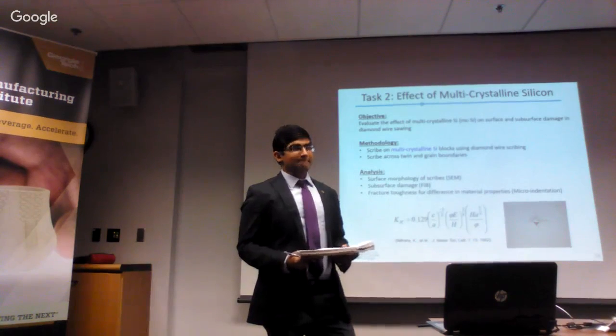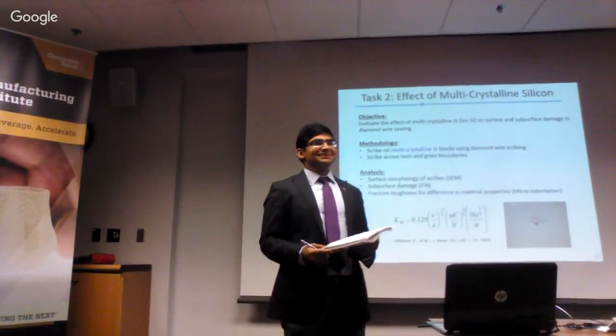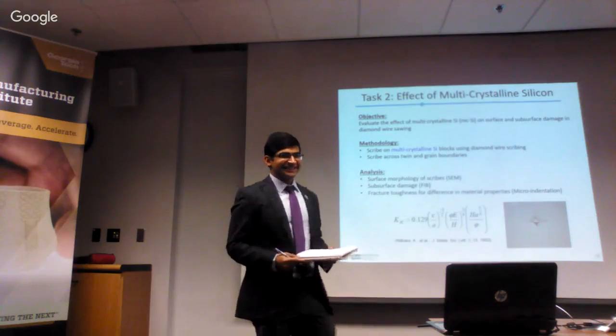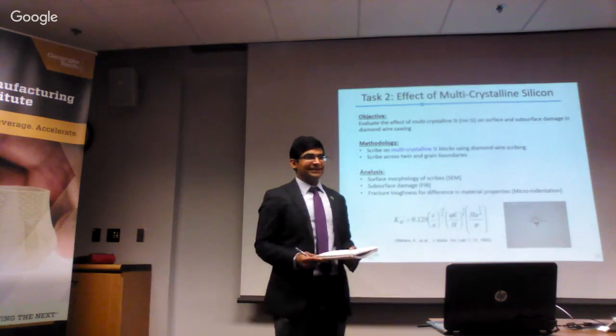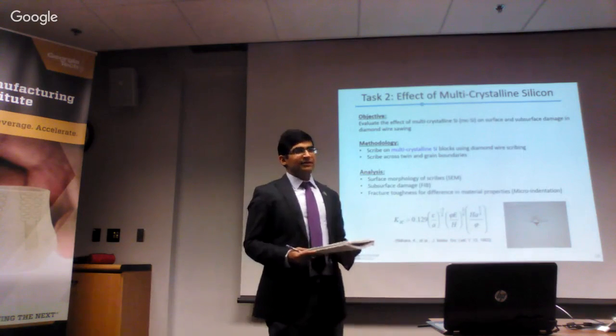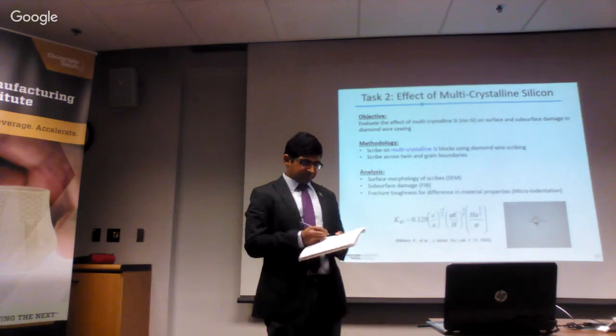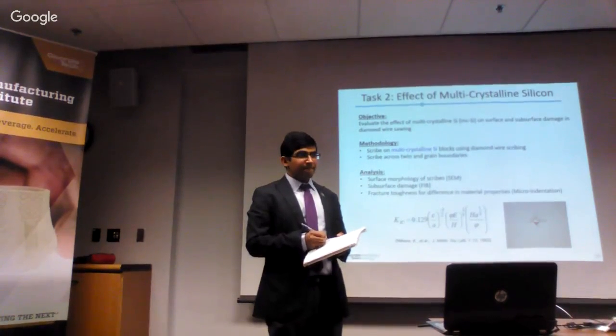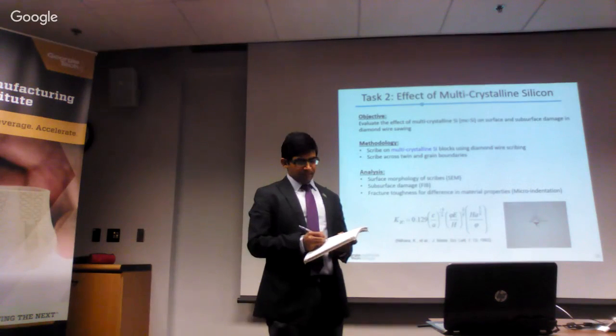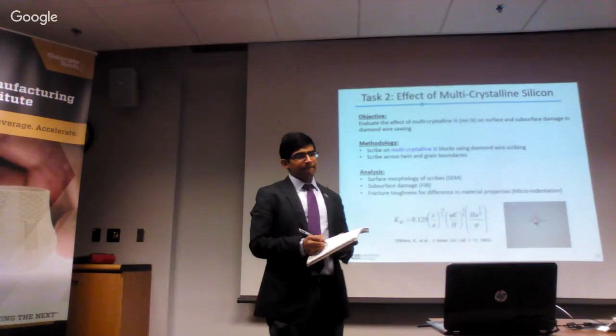I'll make one more comment about this, and we've got to get off this topic. The reason we in my group never pursued this dislocation explanation is because dislocations are not active in silicon at room temperature. You've got to get up to about 750 centigrade before dislocations actually are generated. So we didn't feel like we could explain it by a plastic deformation process. It had to be some other process. That's the way we interpret it. But what do you have to say to that?